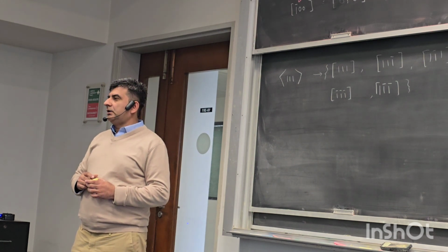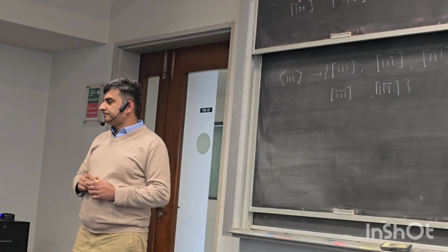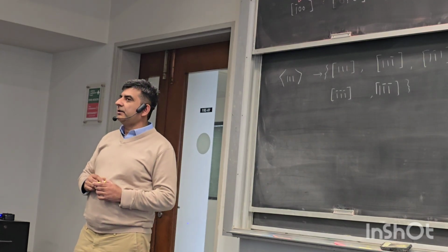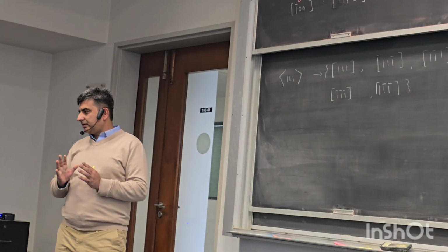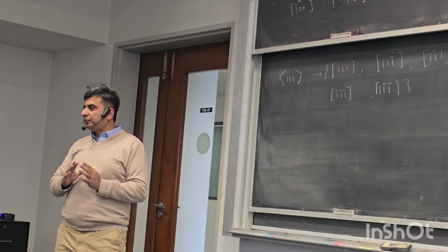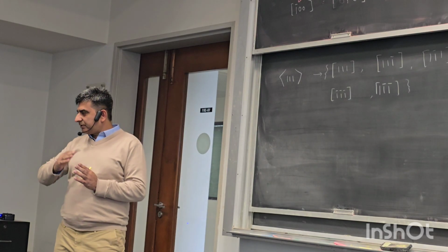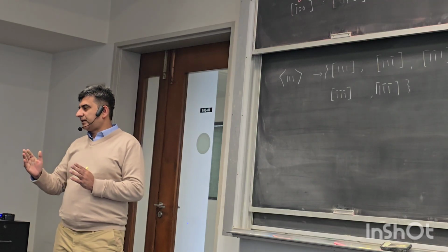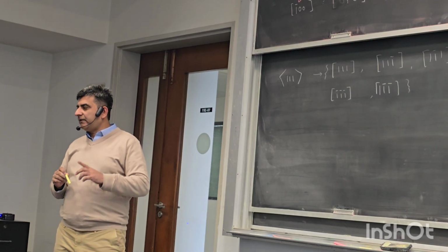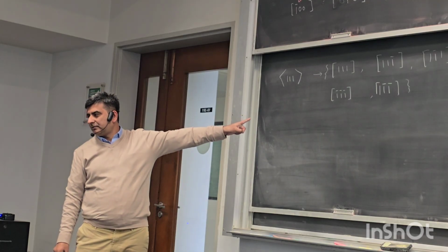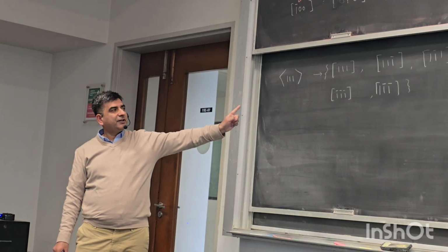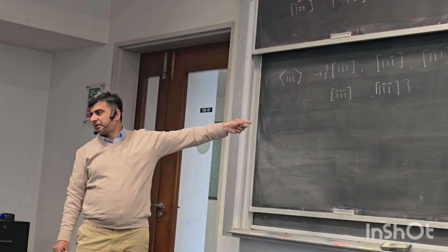No, that's not true. So only when you have a direction and then you move along a unit translation, you will get the same distribution of atoms. However, if you have directions belonging to the same family, then you will have the same distribution along all directions in that family.